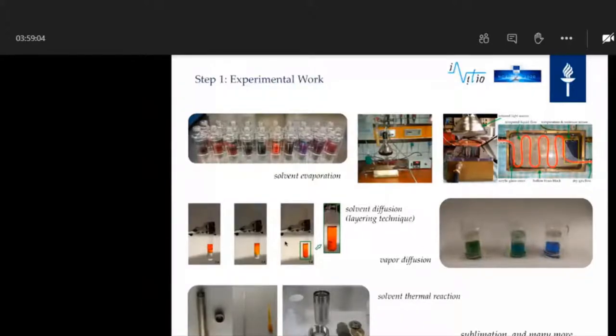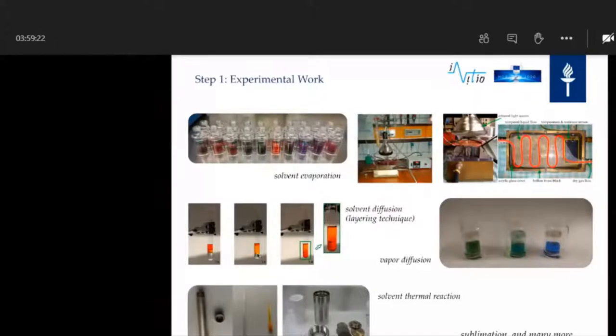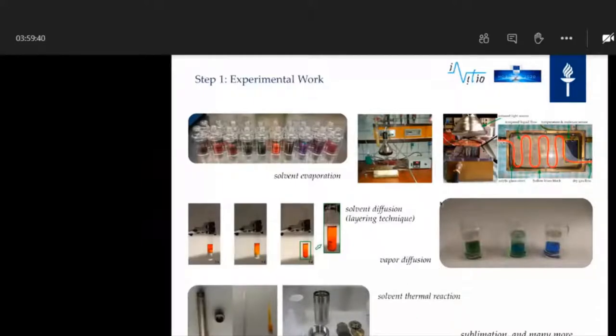Then there is the solvent diffusion layering technique, where in the lower phase you have component A and in the upper phase a different solvent with component B. In the intermediate layer of both solvents, you get slow diffusion of both components, and at some point the product crashes out because it's no longer soluble in either solvent. The same principle applies in vapor diffusion. You can also use solvothermal reaction, sublimation, convection, and many other ways to obtain crystalline material.